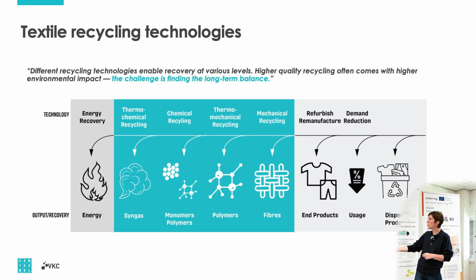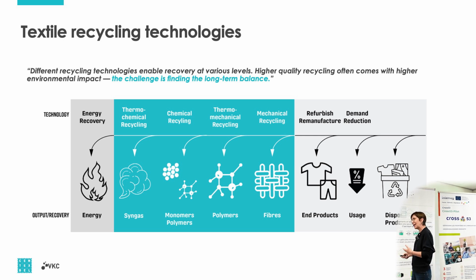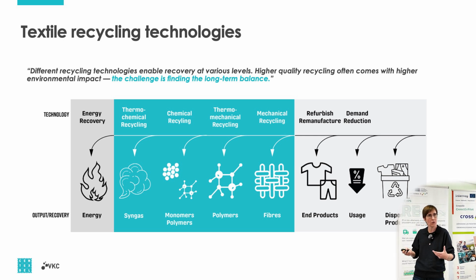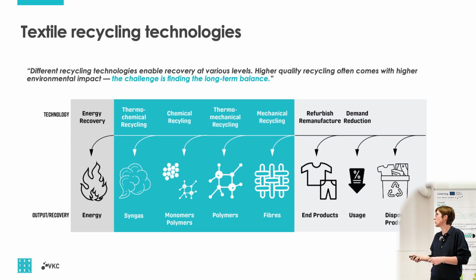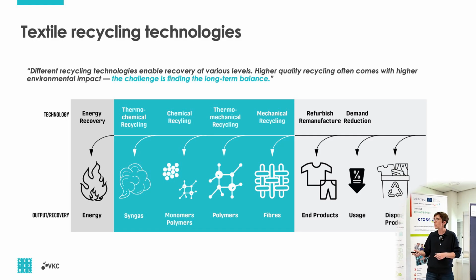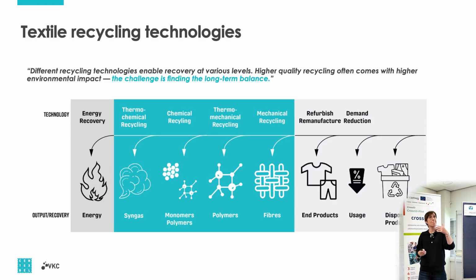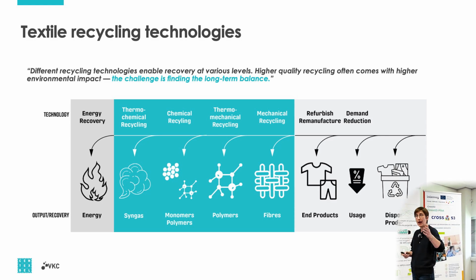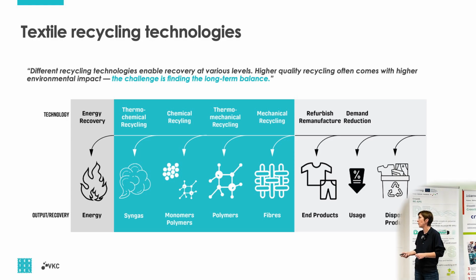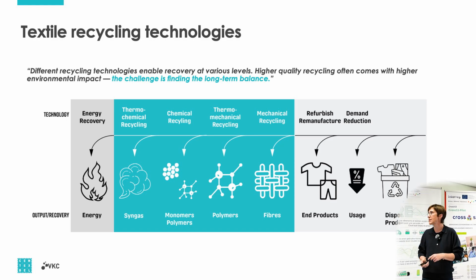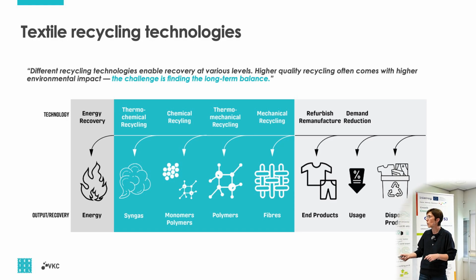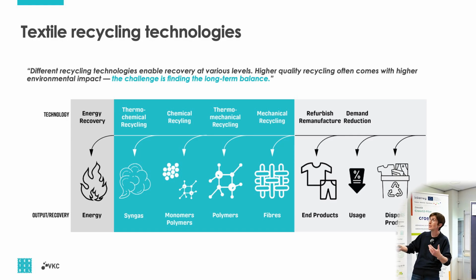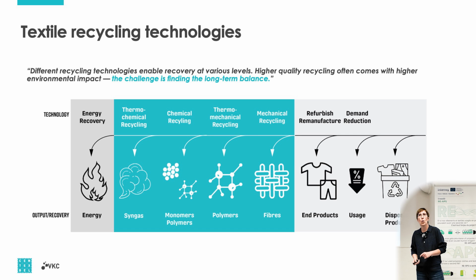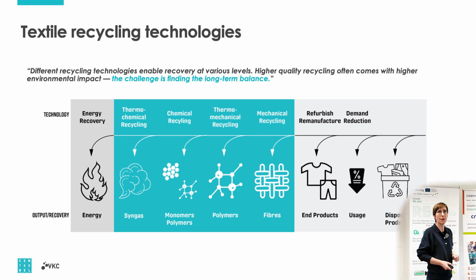In the loop is what we will focus on today, thermomechanical recycling, because it can happen that the fibers after mechanical recycling are too short and you're losing the mechanical strength of those materials, so they don't have any use anymore. In that case, we try to go to thermomechanical recycling, where we use the polymer, melt the polymer, and go back to fiber spinning. So from fiber to fiber, but with recuperation of the polymers. If this is not working, you can say, let's depolymerize our polyester, let's do chemical recycling, and then thermal recycling. This is, of course, the pyrolysis processes, where you go back to syngas. The last step in the whole story is that you only go to incineration. Is it a one-to-one solution today? Probably not. I think this is an important first remark.